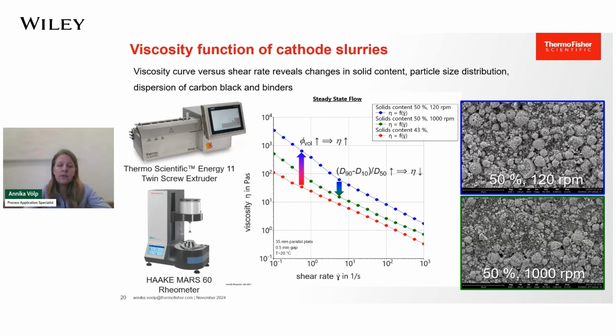This effect is attributed to a broadened particle size distribution, as emphasized by the SEM images that you see here on the right, of the dried slurries when they were coated. A broader particle size distribution might not be necessarily beneficial for the battery electrochemistry, but in general, it would reduce the viscosity of the suspension.